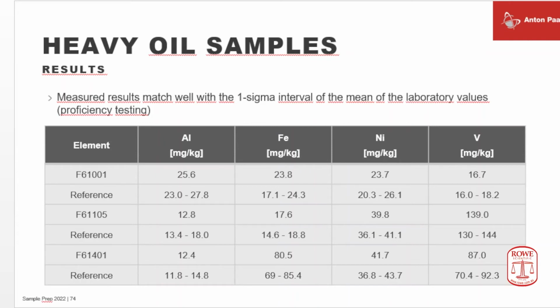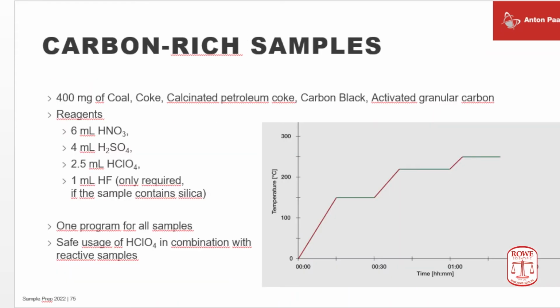Other types of carbon-rich samples may be coal, coke, petroleum coke, carbon black, and granular carbon in the form of active carbon granulates. Again, you see in this case a three-step procedure, stepwise, slow approach to a maximum temperature, and you see a time duration of 1 hour 15 minutes. So this is really a long time for a microwave, because usually you like to take the microwave to do short processes of 10, 15, 20 minutes. For such tough sample materials, it may take more than an hour to get them destroyed.